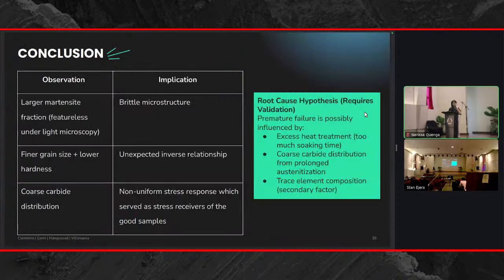Right. So for our conclusion, for our findings, the first is that we observed a difference in characteristic microstructures between the failed samples and the unfailed samples. It implies therefore a brittle microstructure and an unexpected inverse relationship between what's supposed to be finer grains contributing to stress. So the coarse carbide distribution was also greater in the failed samples, and this led to non-uniform stress response in the bad samples as to what they should have been normally in the good samples. So ayan.